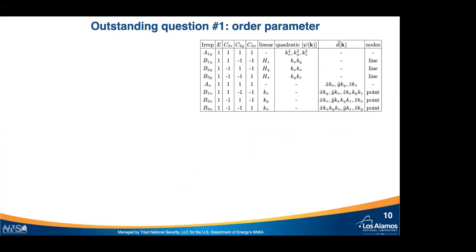So this all makes sense to me, and this actually helps us understand some of the outstanding questions in the field, because now we know that we may actually be close to a quantum critical point. We may be close to an antiferromagnetic instability, and that changes a lot of the constraints. And if we look at all the irreducible representations of this space group, there are many possible combinations here. So we know that we have two superconducting transition temperatures. So we have to choose two of these irreducible representations, but it's not so easy, right? We need extra experimental input. And now we have that.